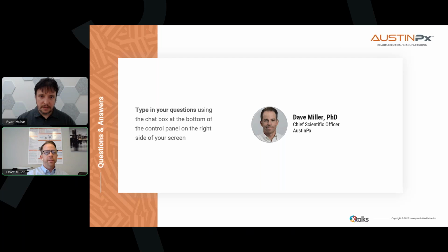This is a strategy we've employed with different formulations, adding performance enhancers extra granularly. Most often this is surfactant materials. We've also added cyclodextrins extra granularly as well, to great effect. The driver for doing that can be different. The incompatibility issue tends to arise most often with something like sodium lauryl sulfate. It just tends to be very reactive. A lot of drugs are incompatible with SLS in the amorphous state, especially at elevated temperature. And SLS, although it's a pretty aggressive surfactant, is not preferred in oral formulations, but sometimes it really is the key towards achieving target performance. So in those cases, adding SLS externally to the granules has been a very powerful approach. So anytime a surfactant material tends to be reactive with the drug, that's a strategy that we've utilized.